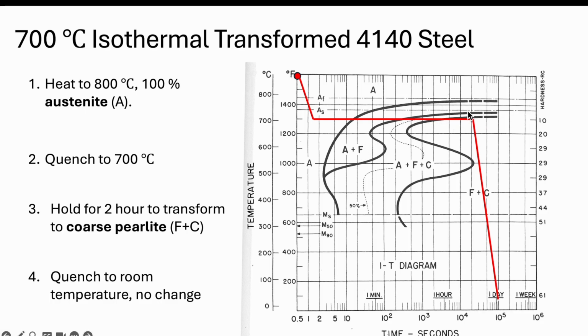And so what happens if we're in that region and we never form pearlite, what happens is that when we do this quench, so when we do this final quench, we would actually form martensite. And martensite has a drastically different microstructure and mechanical properties. And so we can always tell in the lab when this goes wrong, because up here you might notice that we have hardness. So this gives you a rough idea of the hardness. So this coarse pearlite should have a hardness of around 10 on the Rockwell C scale. But if you notice down here, martensite can have a hardness all the way up to 60. So if the temperature is even off by a few degrees in the furnace, we can actually see this sometimes. So sometimes instead of getting a hardness of 10, we might get somewhere up close to 60. So that's one of the things that can happen.